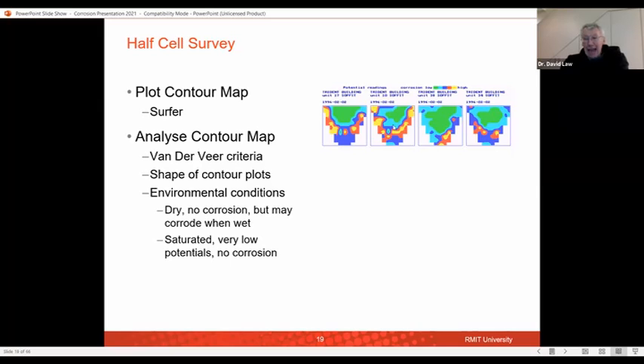And then we get these contour maps. And you can see here, we've got these green zones where the potentials are more likely to be in the passive range. And then we've got these red and yellow zones where they're more likely to be in the active range. And thus we can see we've probably got the green is the cathode, the red and the yellow are where we've got anodes. And if we can't see any cracks or rust yet, we're suspicious that we actually have got corrosion going on.